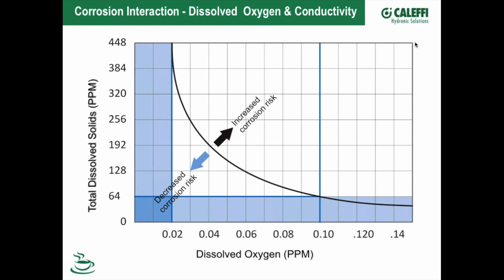If you have a high level of dissolved oxygen concentration in your system before you start up, let's say, all right? Let's say it's off the charts high, all right? What happens through the process of putting a high-performance separator properly placed is that that water is going to either undergo a pressure reduction, which will bring it out of solution in the form of non-dissolved air, or the temperature will be heated up, such as coming off of a boiler, creating microbubbles. And as a result, air separators scrub the water of dissolved oxygen this way.